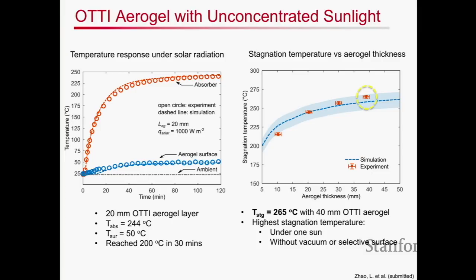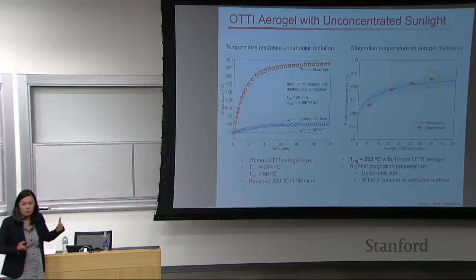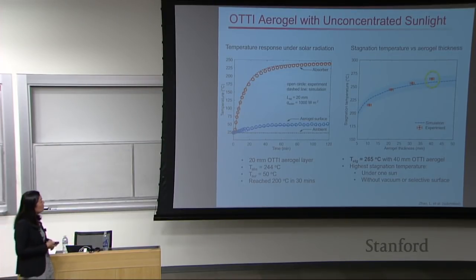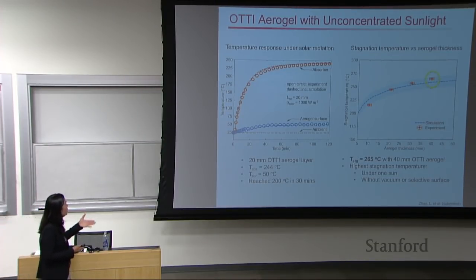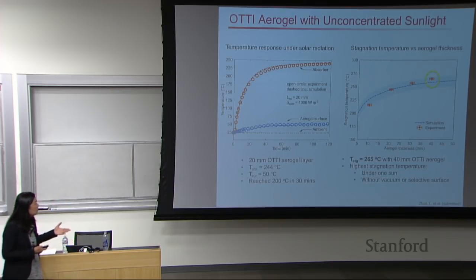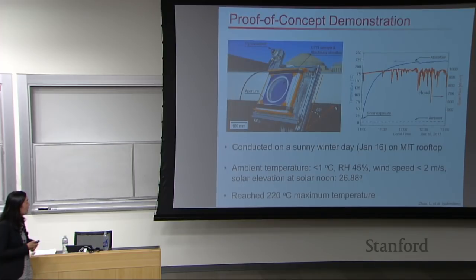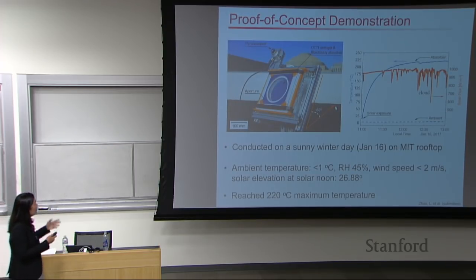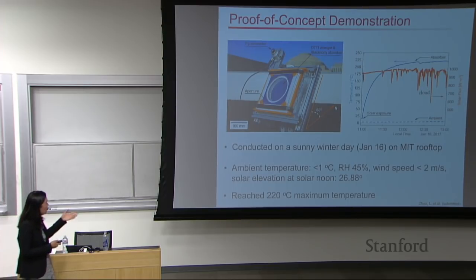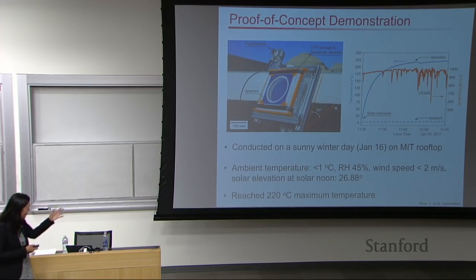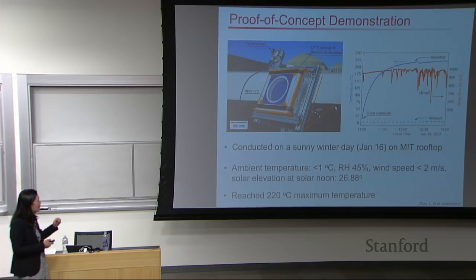And if you compare it to what's been demonstrated with vacuums, it's very difficult to even reach this at relatively low cost. So we've been excited about these kinds of material sets that we've been able to create using these optically transparent thermally insulating aerogels, and we've now been able to demonstrate it in an outdoor setting. This is, in fact, during a cold winter day, although sunny, in Boston on a rooftop. You can see the ambient is pretty much close to zero.